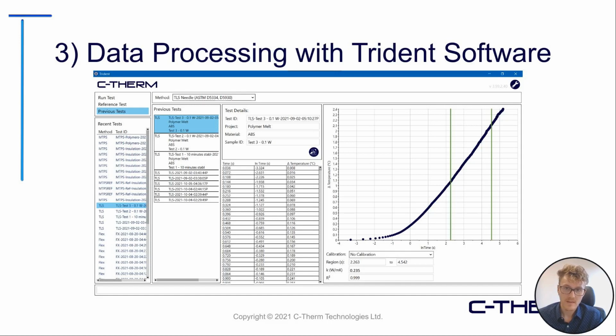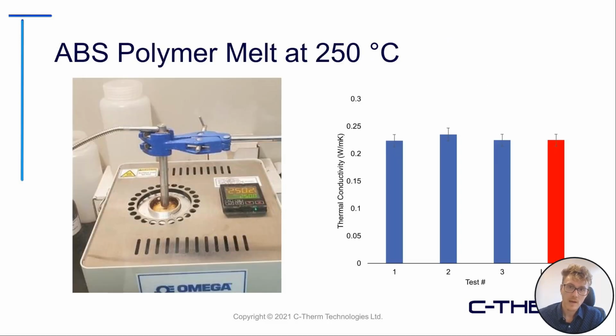And at the end, you'll see your thermal conductivity value there. The software is very easy to use, and you're able to get multiple replicates of measurements as shown here. And what we can see in this final ABS polymer melt data is that we have a very precise and accurate measurement as compared to literature values. All the measurements are well within 5% of the literature value, showing a very robust system for measuring this sample.